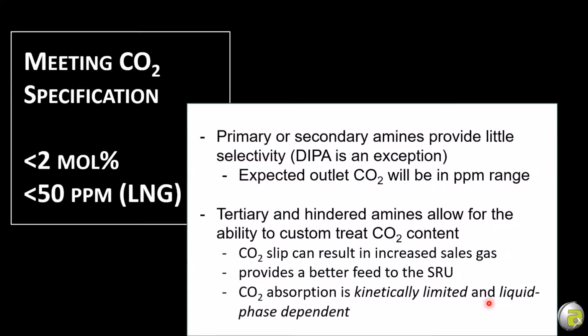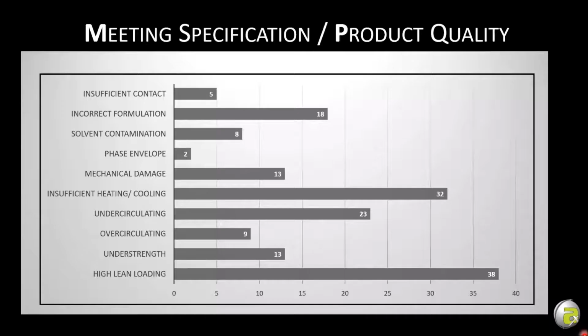H2S absorption is rapid, almost a surface reaction, whereas CO2 is more bulk fluid reactivity. So CO2 removal depends a lot on how much amine I pump into that tower, or how high the weirs are in our tower to give us a higher liquid level on each tray. So we say it's liquid phase dependent. Now, what did the database tell us about meeting spec?